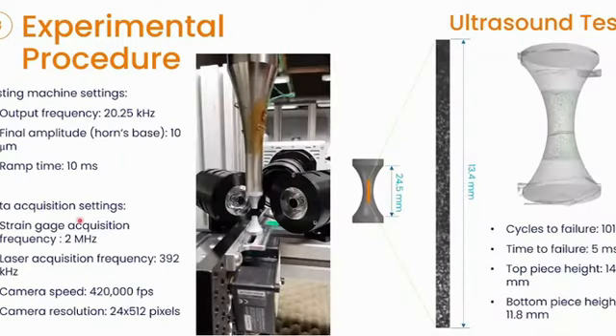And then in the ultrasound tensile testing, the machine was set up to get to a maximum of 10 micrometers of amplitude of vibration at the horn's base, and it should take 10 milliseconds to reach that amplitude. The camera had a recording speed of 420,000 frames per second, and a resolution of 24 by 512 pixels, which allowed the camera to capture a zone of 13 millimeters at the center of the specimen.